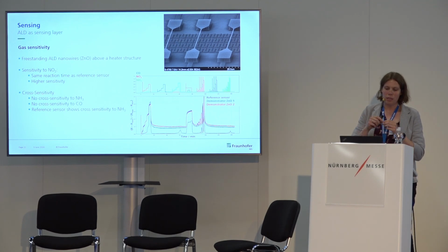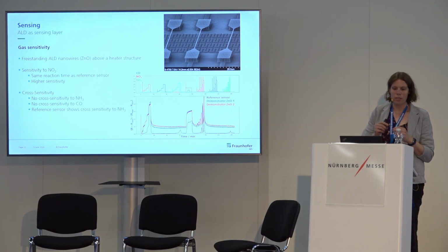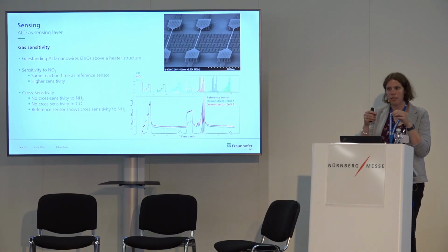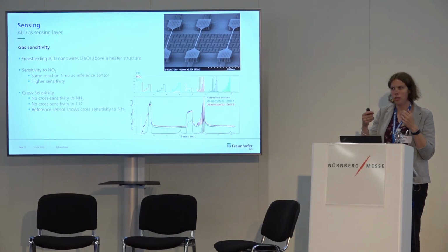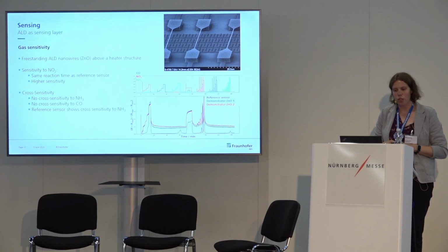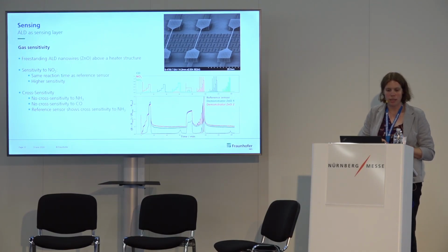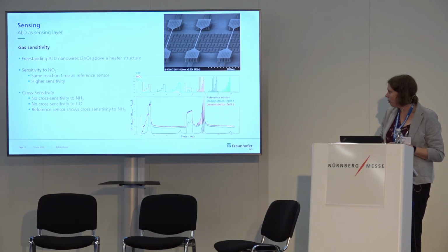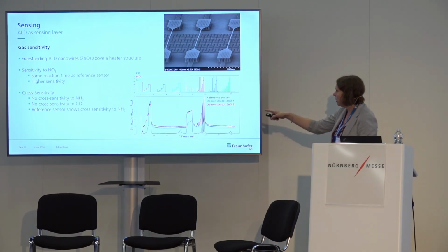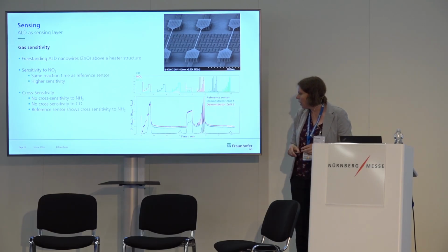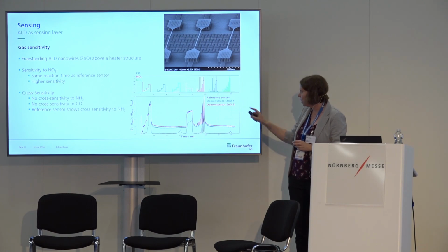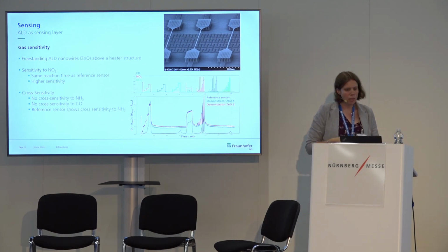So we have these ZnO nanowires above a heater structure, and we checked them. So if gas is on the surface, the resistivity changes, and we checked these sensors against a reference sensor, which is shown on the bottom. And here on the top, you see the incoming gas. And here the reaction of the sensor. So in black it's the reference sensor, in blue and red are our demonstrators.